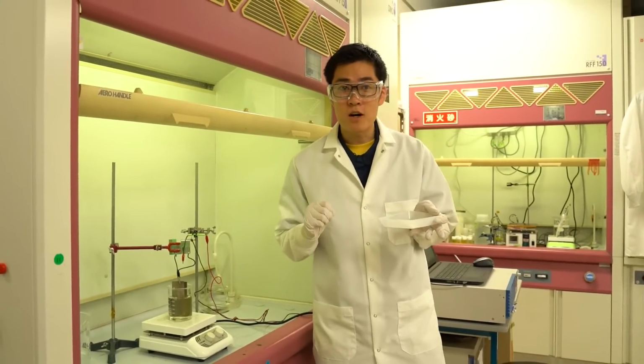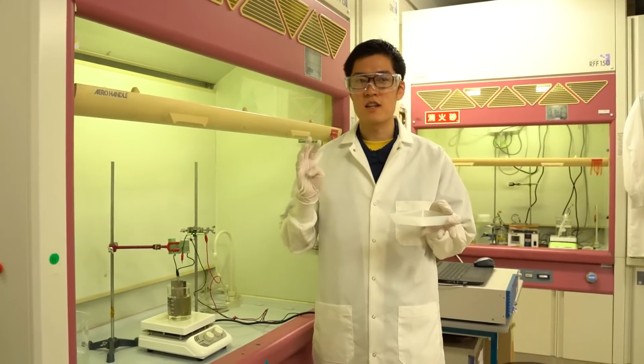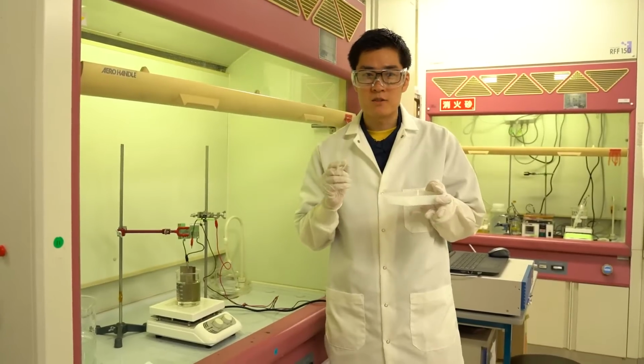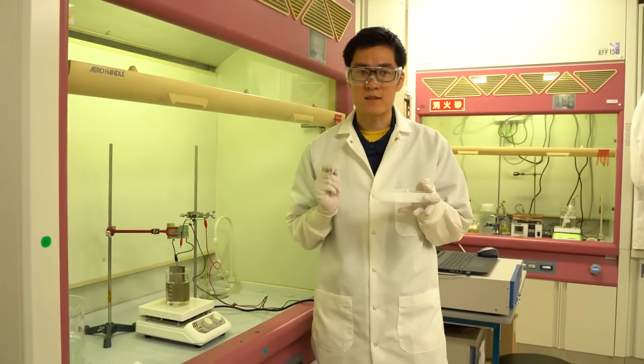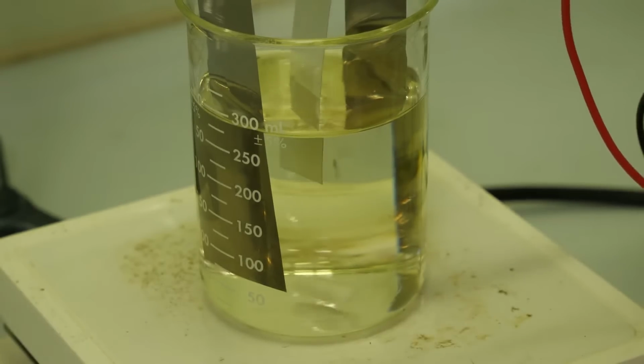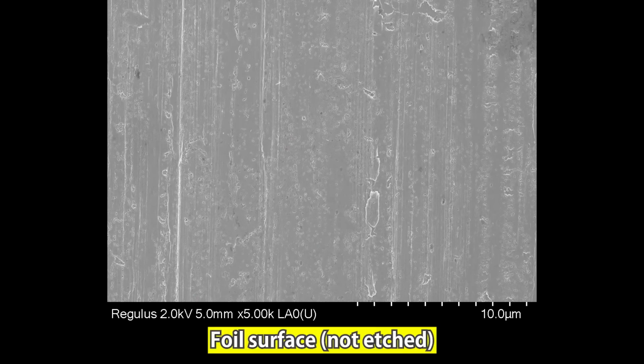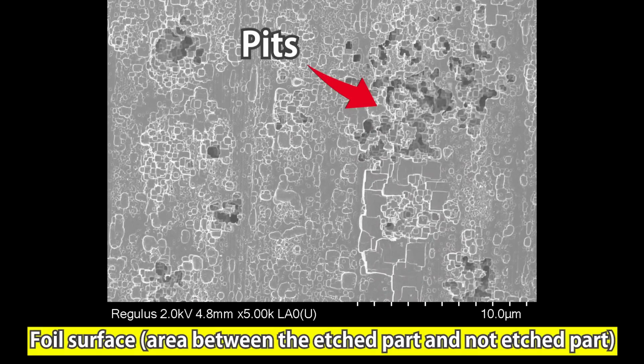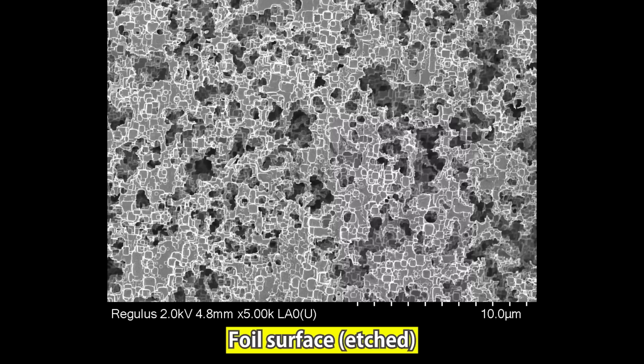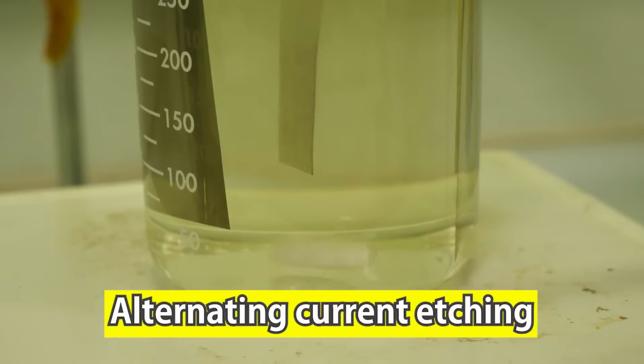The reason why electrolytic capacitors have a larger capacitance than other capacitors is because the surface area of the aluminum foil is large. I'll soak the foil in this etching bath. This will create fine pits on the foil's surface. The pits don't go through the aluminum foil. When those pits are created, the surface area of the aluminum foil is expanded. The foil is being etched in this bath.